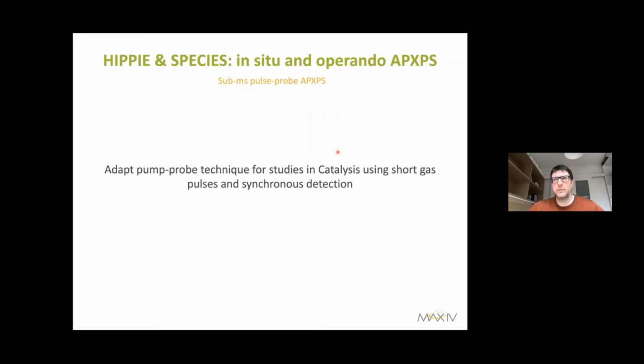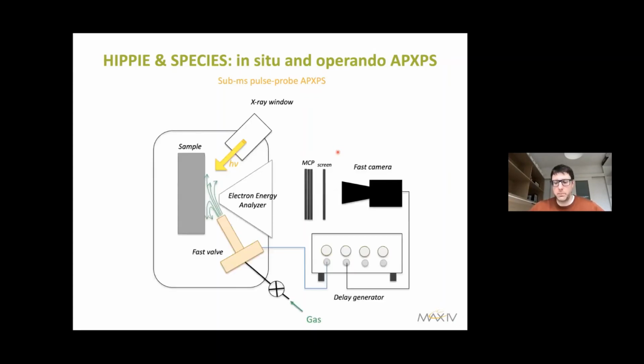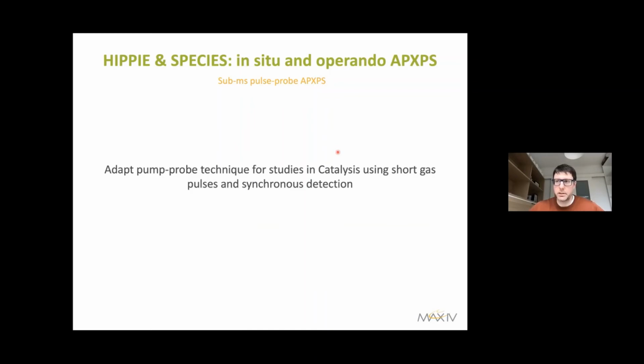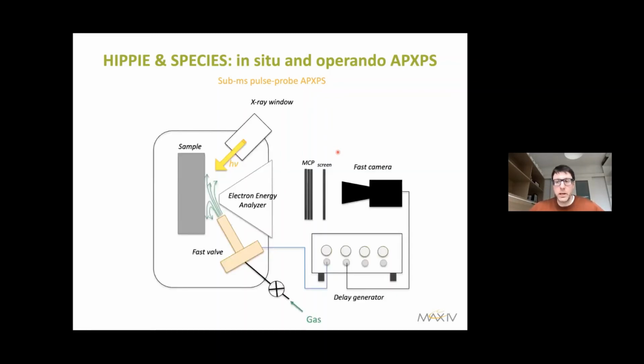We need a pump-probe technique, which I'm sure all of us know from typical pump-probe experiments used in the field, where you have a laser as a pump and then a very short probe by X-rays to study ultrafast phenomena. We can do the same in principle with XPS, but instead of using a laser pulse, we can use pulses of gas.